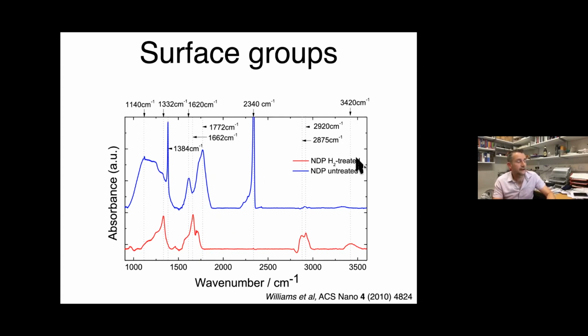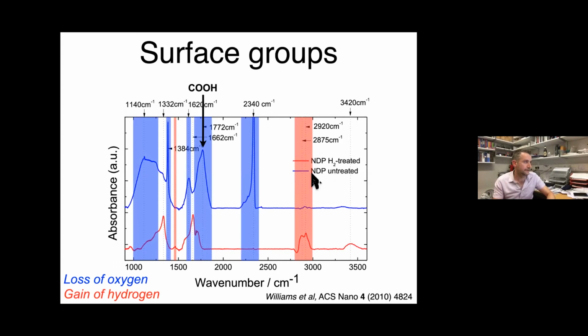And if you look at the FTIR, this is the thing that was really interesting and caused a lot of controversy and fights over a few years. I'm going to skip through all the boring peaks and just go to, here we go: when you anneal in hydrogen, you're able to remove these COOH groups from the surface. You reduce those, and then you see the CH groups, right? So this is where it gets really interesting.